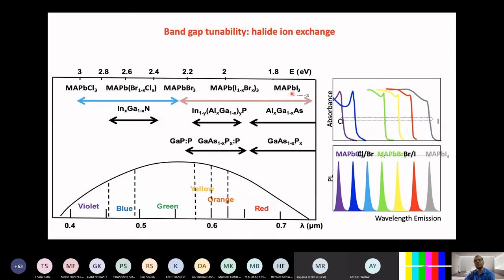This is MAPbI3. When I replace iodine with bromine, 1 minus X and bromine X, then I can tune the band gap in this range. This is pure methylammonium lead bromide. If I replace bromine with a little bit of chlorine, then I can tune my band gap with this blue arrow, and you can get the pure 3 electron volts color from the methylammonium lead chloride. So you can tune the band gap all the way from UV to NIR range by very simple chemistry. It's like you are just adding different salts together, and everything happens spontaneously.